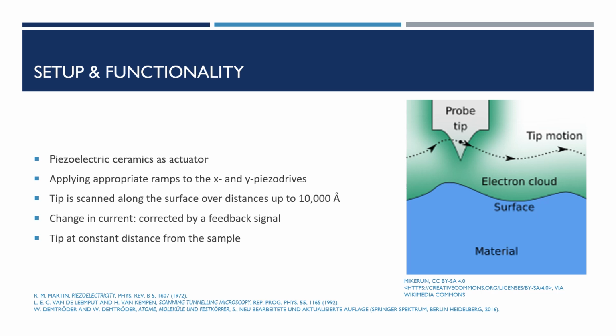So the tip is scanned along the surface and follows its contours. The feedback signal yields directly the topography of the surface, as you can see on the figure on the right. Besides the constant current mode, there are further modes, like for example the constant height mode. An advantage of this is that it can scan faster, even produce real-time images, but there is also the risk of a collision with the surface of the sample. You can also do spectroscopy, which was the original idea of Binnig and Rohrer.